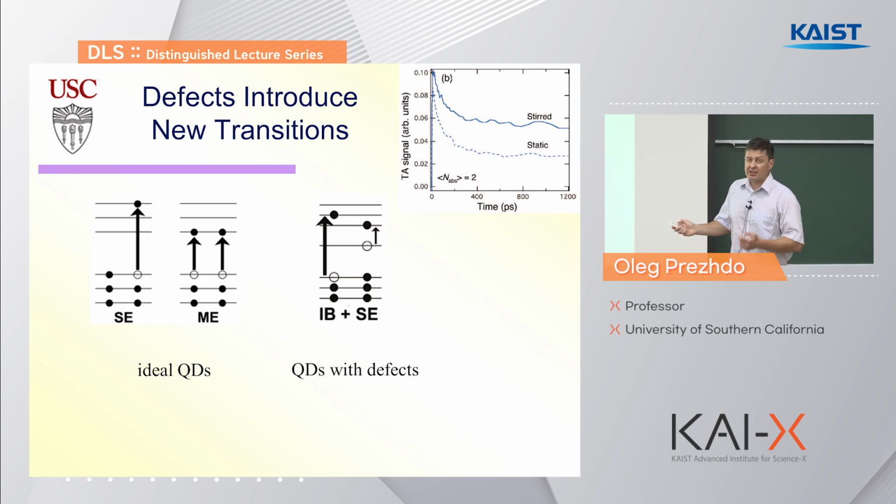So this is your double excited state, but this is not the state that you need for solar energy, because to make it balanced, to make charges flow, you need the same number of positive and negative charges. They have to balance. So this is your double excited state on the right, but this is not the double excited state that you need for this effect to matter. And this happens because your quantum dot is not ideal system. You have some trap states on the surface, and that's why you trap hole, and you have extra electron here that can be excited.